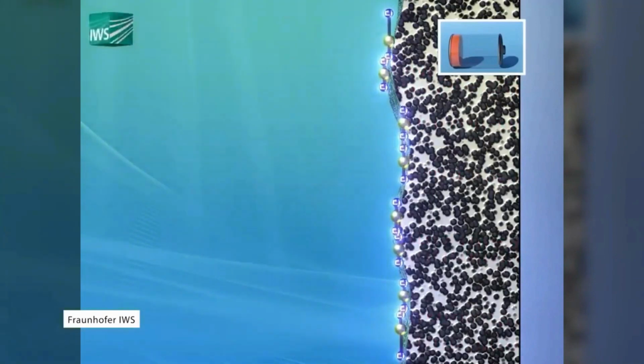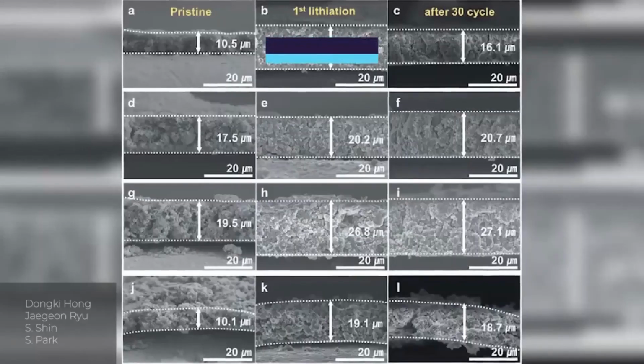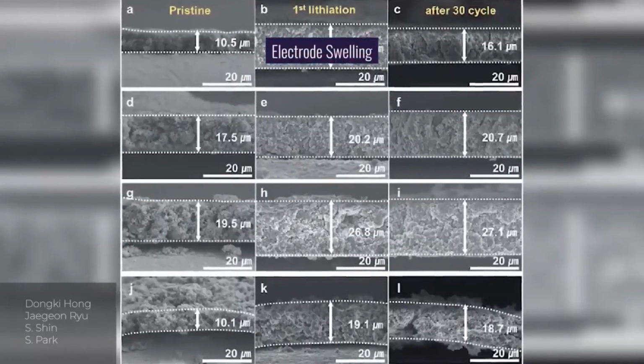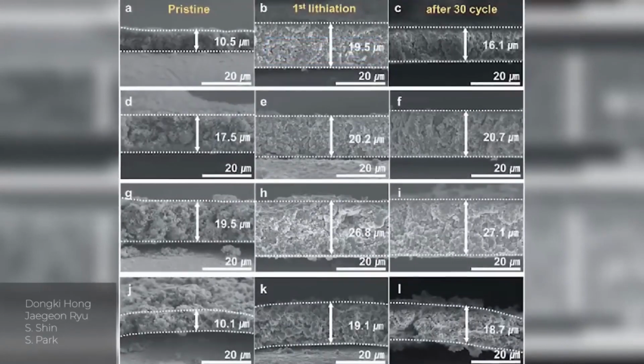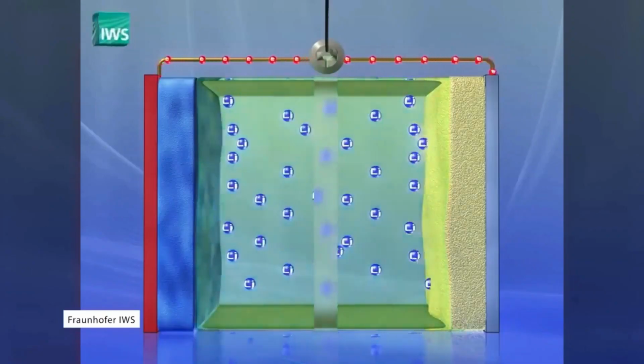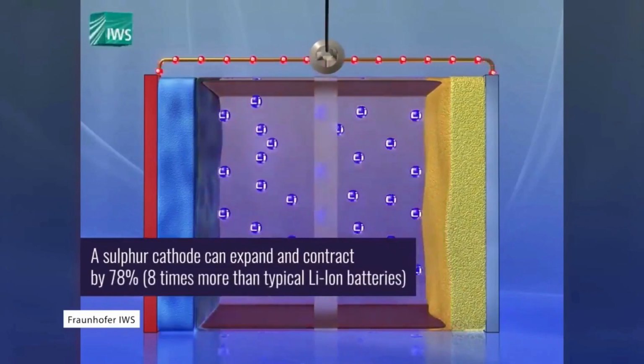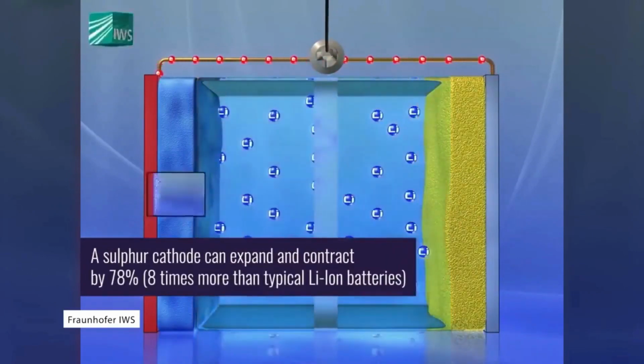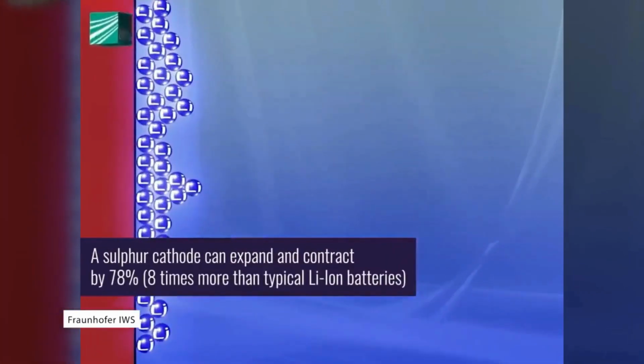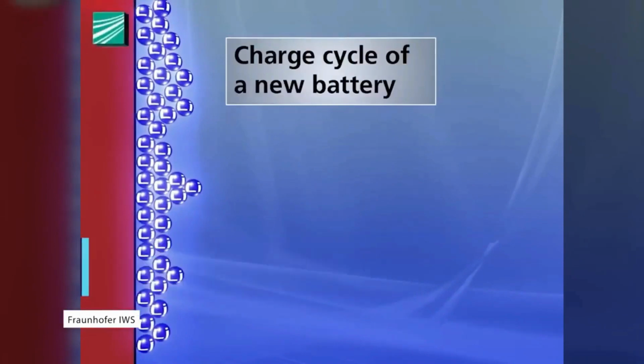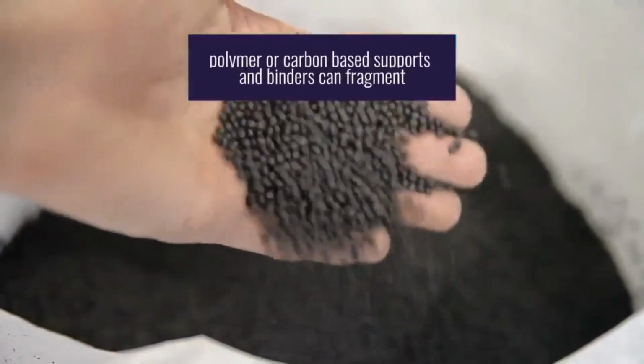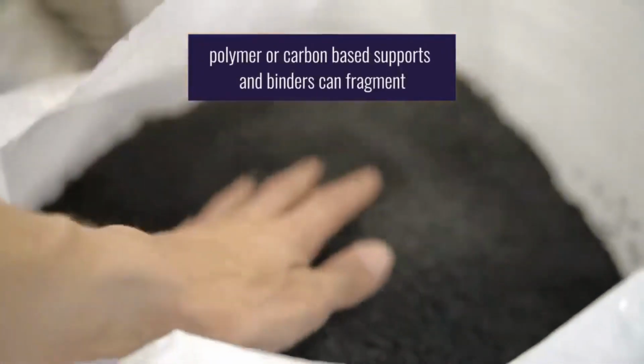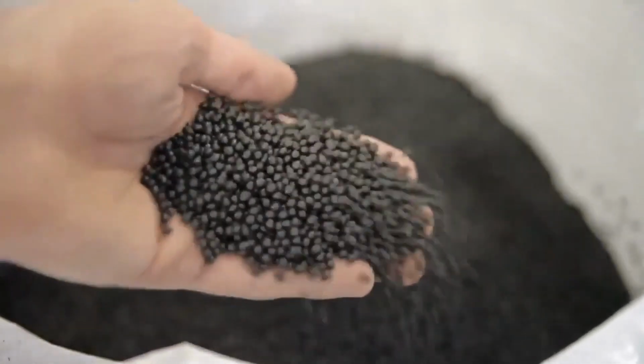Next, and most significantly, the electrodes physically swell up as the lithium ions bond to them. This is more dramatic with lithium-sulfur than existing chemistries, the sulfur cathode expanding and contracting by as much as 78% as the battery cycles, or 8 times more than cathodes typically used in lithium-ion batteries. As might be expected from this kind of repeated strain, polymer or carbon-based supports and binders fragment and can disintegrate as the battery cycles, reducing capacity and performance.